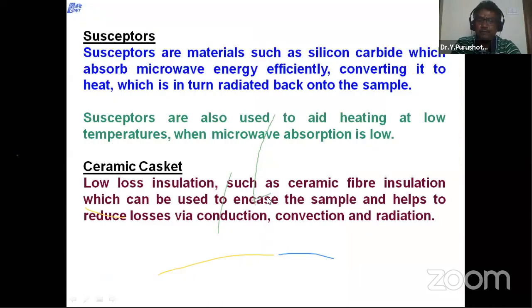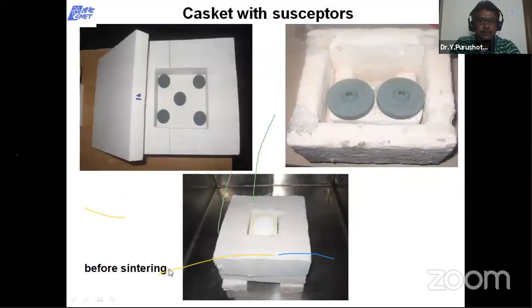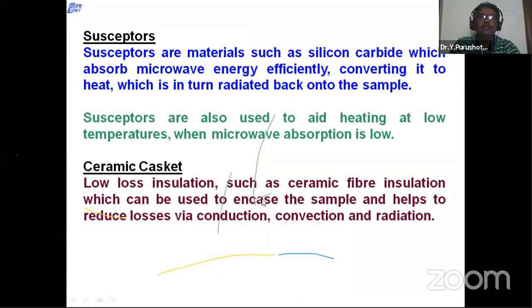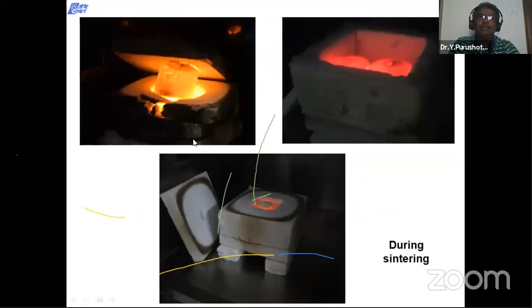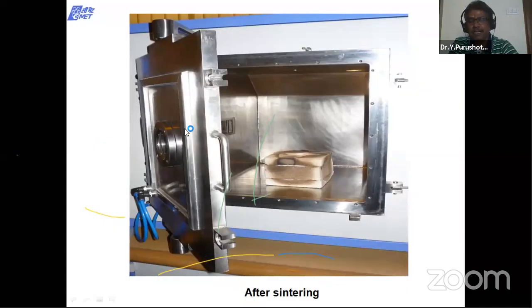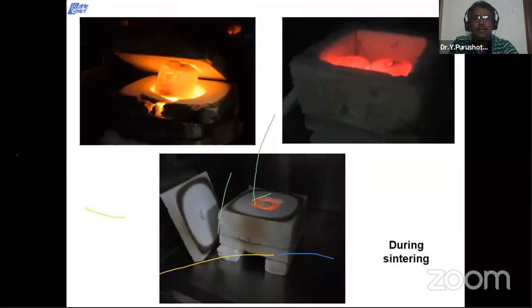So before sintering, it will be like this. We are loading in this way and closing the chamber door. This susceptor is nothing but silicon carbide, which absorbs microwave energy efficiently, converting it into heat, which in turn is radiated back onto the sample. So the ceramic casket is a low loss insulation material. And as I told you, this is very selective heating. Volumetric heating will take place.